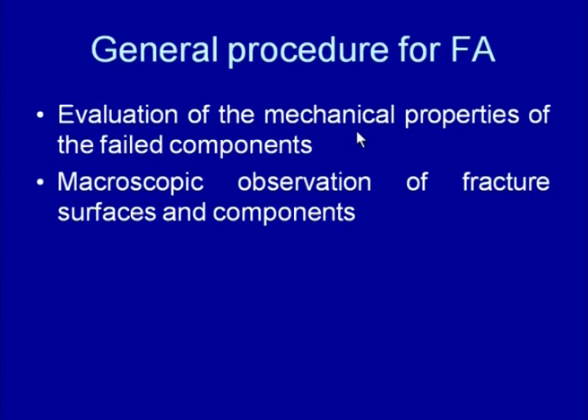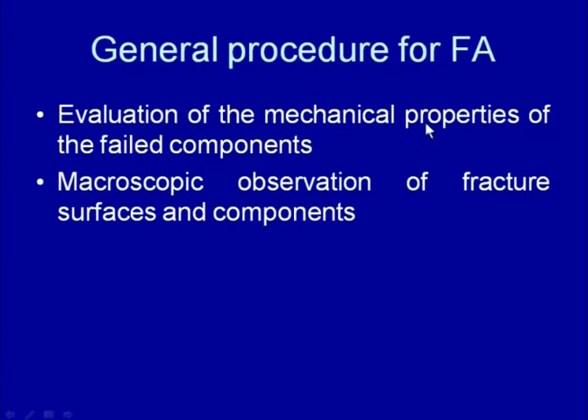These are destructive tests. Mechanical properties of the samples taken from the location close to the fracture surface and those away from the fracture surface can be determined in the form of the hardness test, tensile test, and fracture toughness test. The objective of these tests is to see whether the material which was made for a particular component had the desired set of mechanical properties or not.